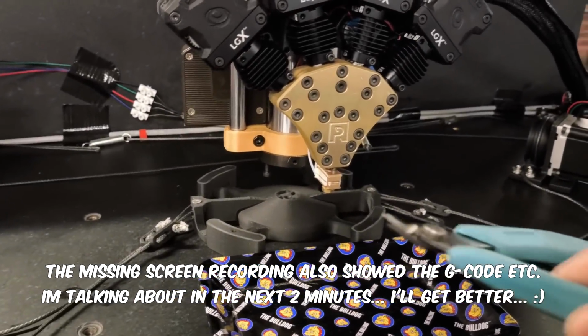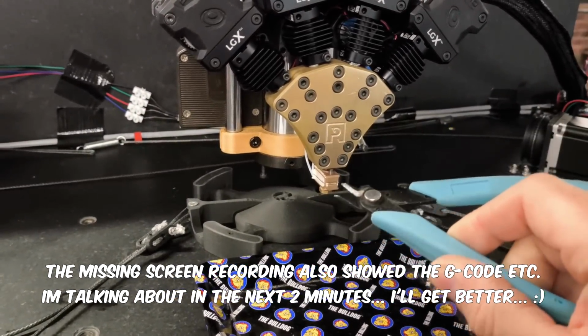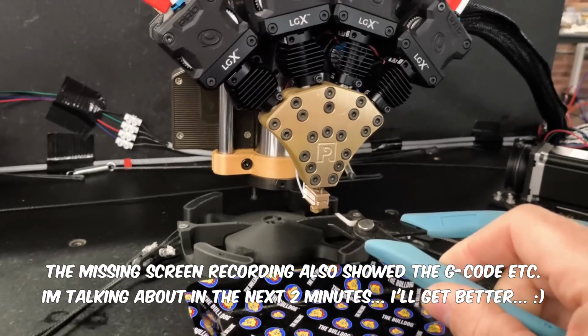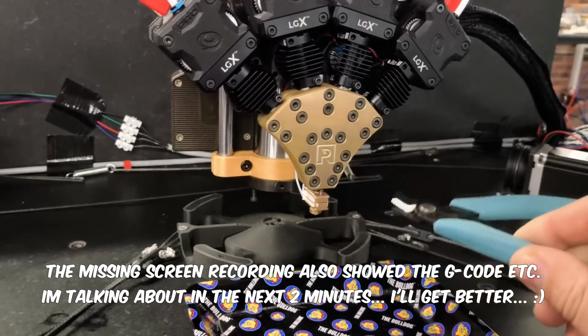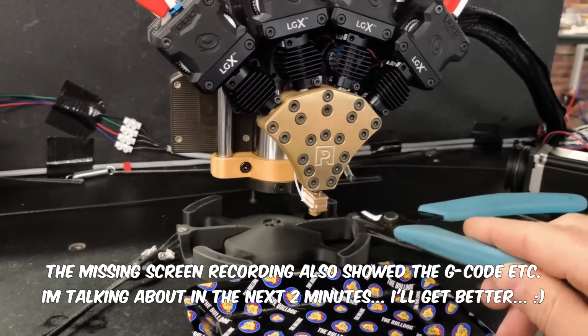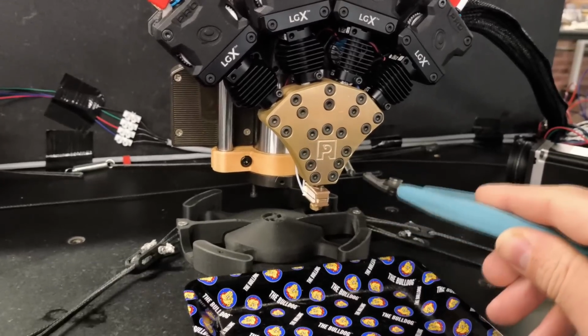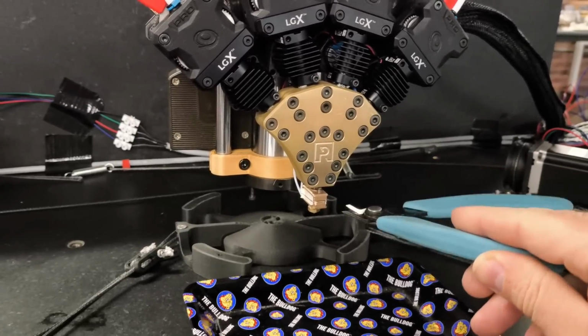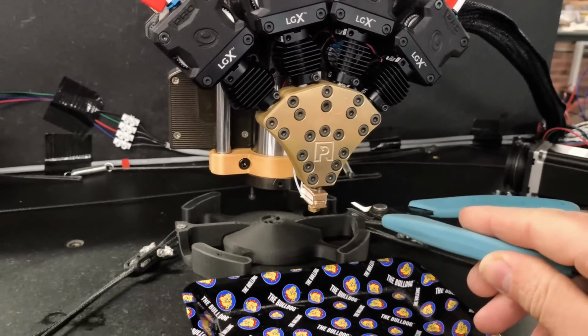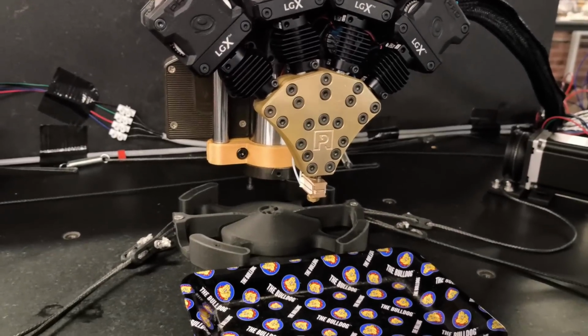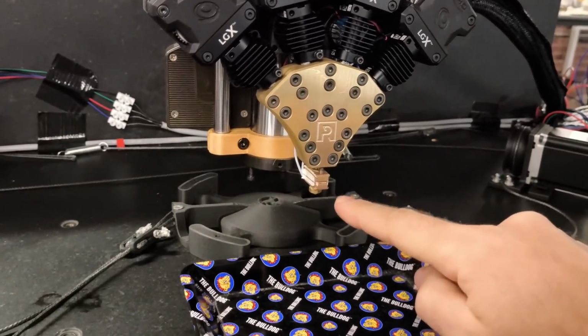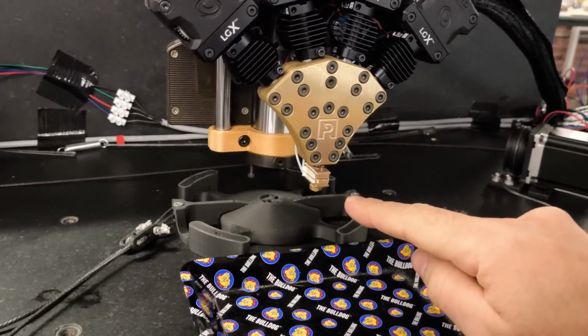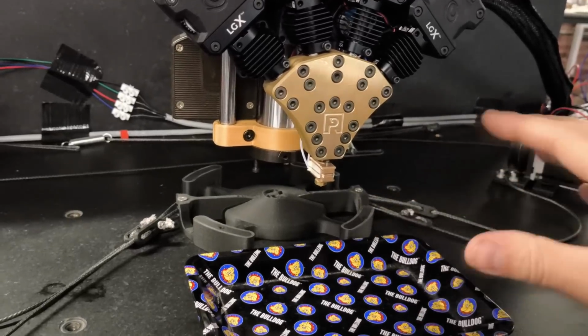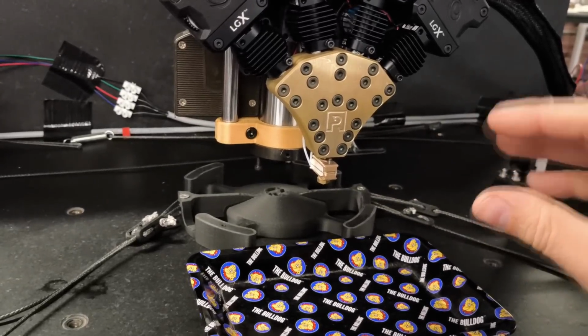I did the testing with just having the upper one going, to see how much it's going to influence the temperature of the lower one, and if it settles in, we have a temperature difference of 50 degrees. So when this was 215, this was somewhere in the 160 range. I think that's right where we need to be, because this will have a lot of active cooling, and then the difference we can actually have in there will be way greater.